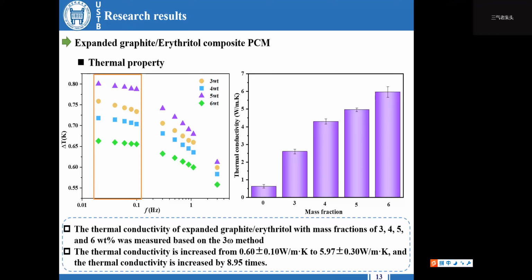Phase-changing materials have the problem of low thermal conductivity. It is of great significance to study the effect of different mass fractions on the thermal conductivity of erythritol in practical applications. The increase in thermal conductivity of erythritol with the mass fraction of expanded graphite was measured by the third harmonic method. The mass fraction of expanded graphite being 0 represents pure erythritol. The thermal conductivity increased from 0.6 to 5.97, which was 8.95 times higher than that of pure erythritol.